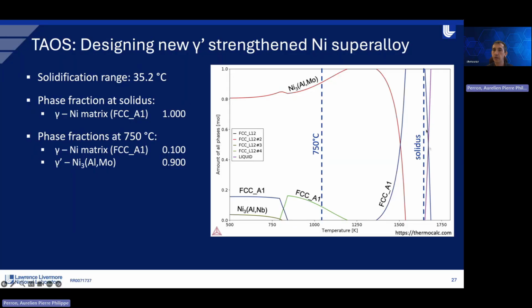At the end of solidification, at the solidus, we are 100% FCC, so we matched that constraint, and we also matched the other constraints at 750C. Remember, we wanted at least 75% of this L12 phase, at least 10% of FCC.